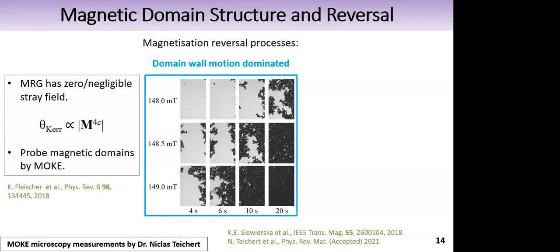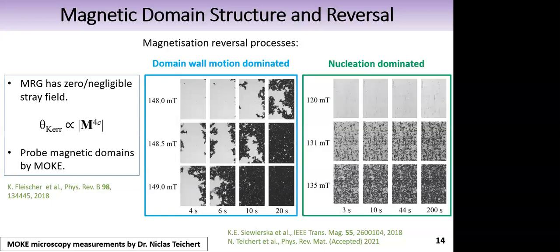So we found 2 different magnetization reversal processes. The first one is the domain wall motion dominated. And here we can see domains that have a dendritic type of structure. The second type of reversal process was nucleation dominated. And this process can be set in the sample by depositing it at different temperatures, but also by varying the composition. So we can control which kind of reversal process occurs.